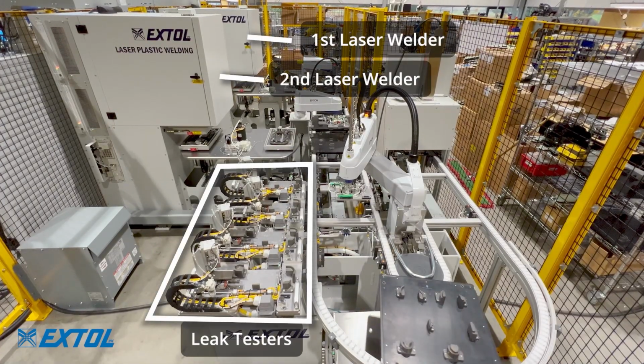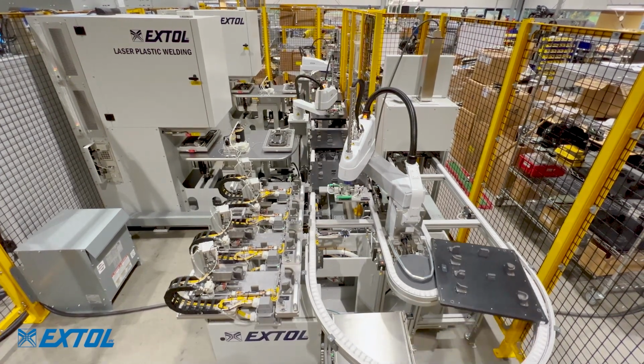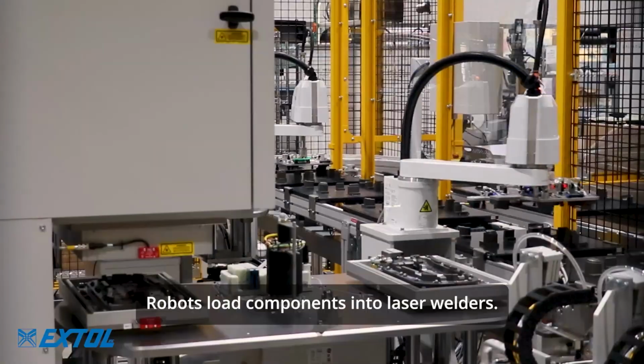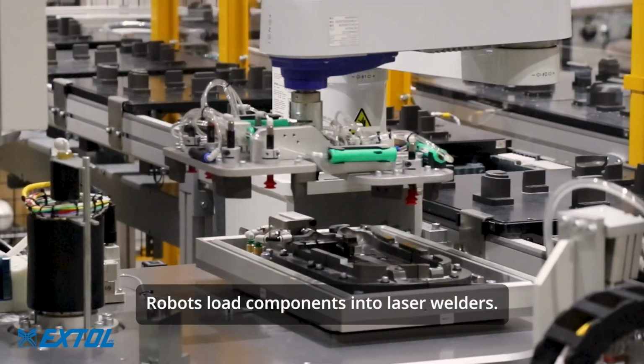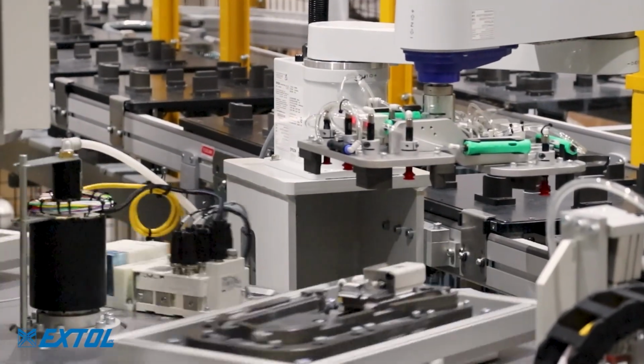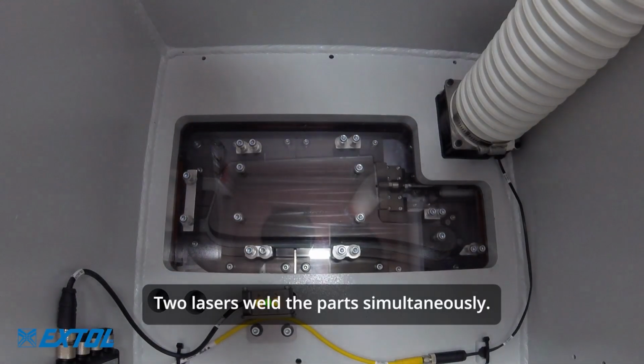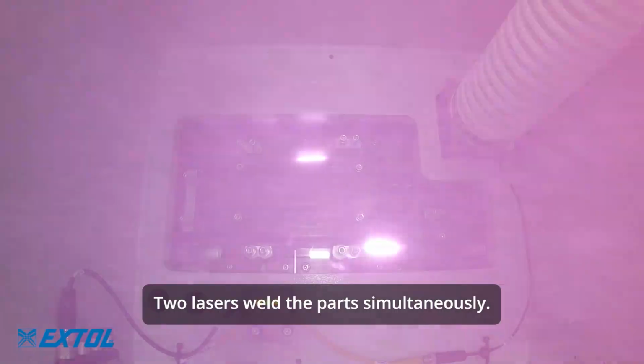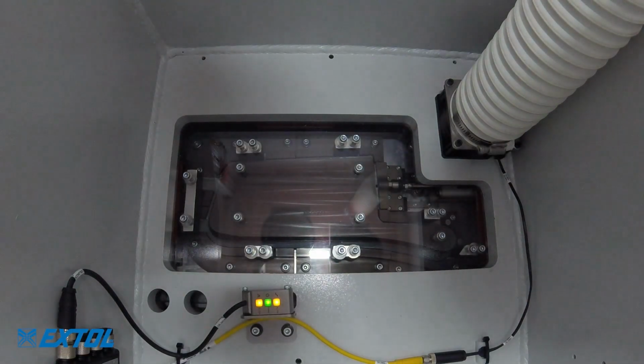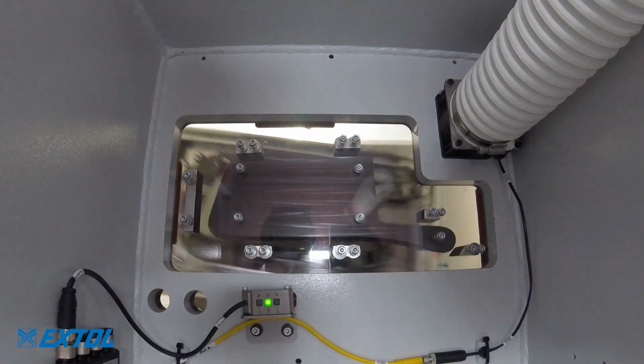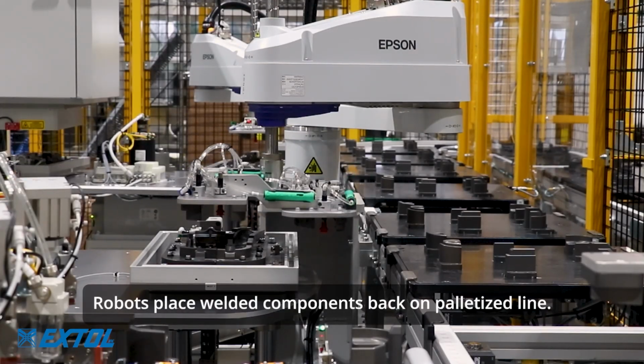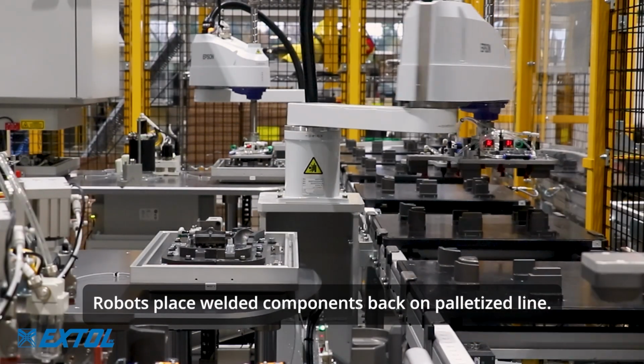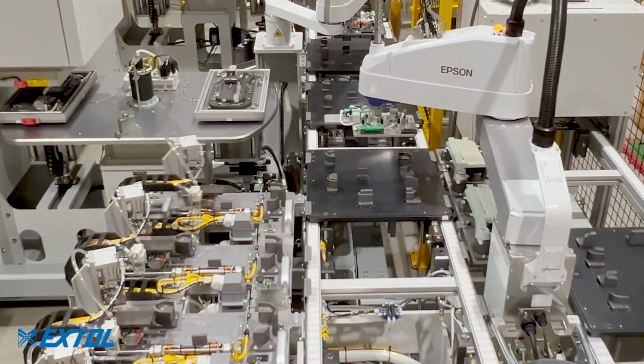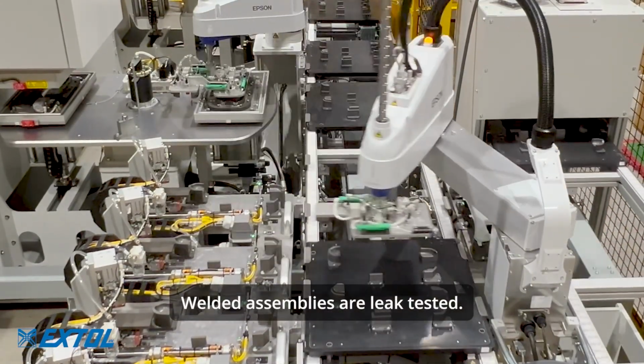It's dry cycling. You're going to see it call out 2 different welding applications or machines. This system had 1 operator, and it would weld a part every, I think, 18 or 20 seconds. One of the key ways we accomplished that was we looked at the application and we said we need 2 lasers at 500 watts apiece to do that work. So we're seeing more and more applications with multiple scanners. In this case, it was a flat part. We can do multiple scanners on different angles. But in this case, it was because we needed speed. And the system would do 2 laser welds.